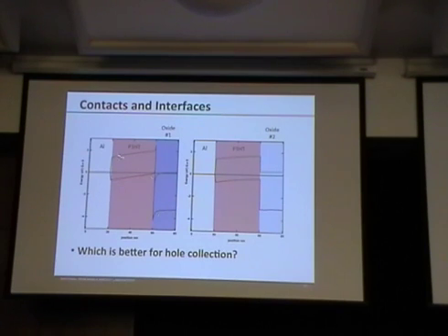All right, so now here I have a quite thin layer, and I've just made it. This came up when Dr. Lee, Gang Lee, was talking a little bit about how some of these deep N-type things can work. So here we have one oxide whose conduction band is very, very far from vacuum. And we have an interface with P3HT. And then we have an aluminum contact. Now, to be fair, this is quite thin, but you can see the band bending. And you can see that this should be not bad for holes.